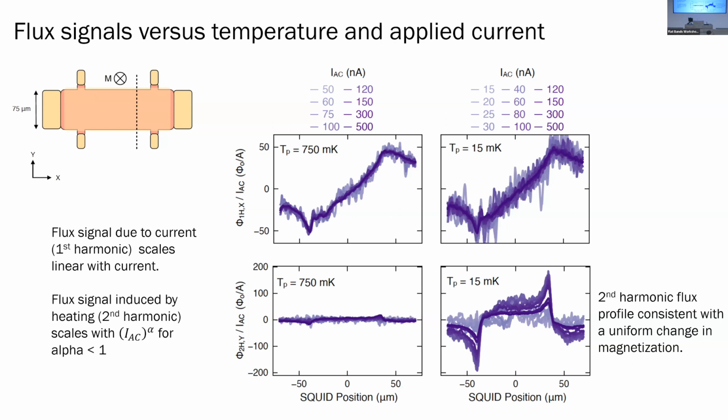In this experiment, our spatial resolution, depending on what criteria you choose, is about 2 micrometers. If there is some percolative path that folds back onto itself very many times within 2 micrometers, then we wouldn't be able to spatially resolve that. But still, there are strong constraints on how such a percolative path has to look, because if you zoom out, the average current density has to match what we see. And then it also has to give you quantization.